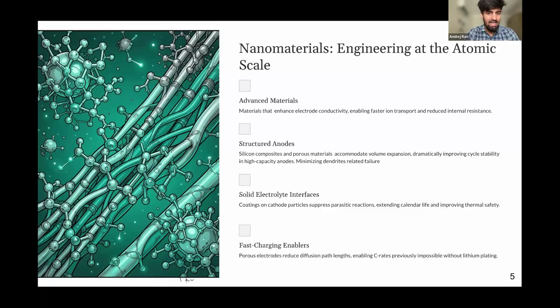Then we also have SEI, the solid electrolyte interface. This happens at the interface of the electrode and the electrolyte. And this again is a very important layer, because this is a protective layer for the electrodes, but it is a result of a parasitic reaction happening inside the battery.